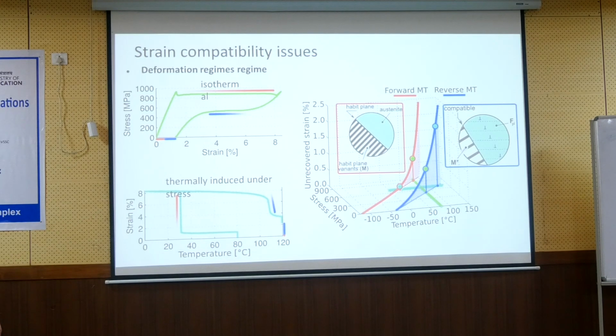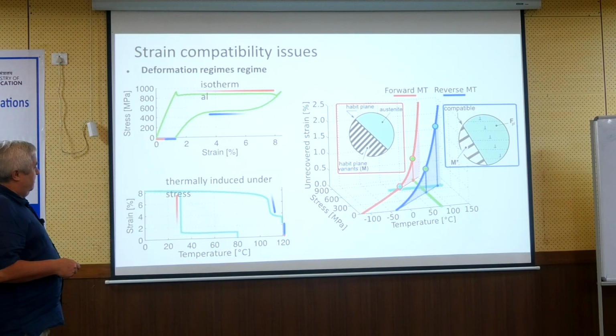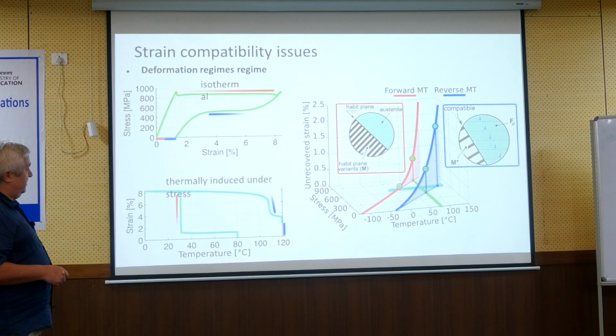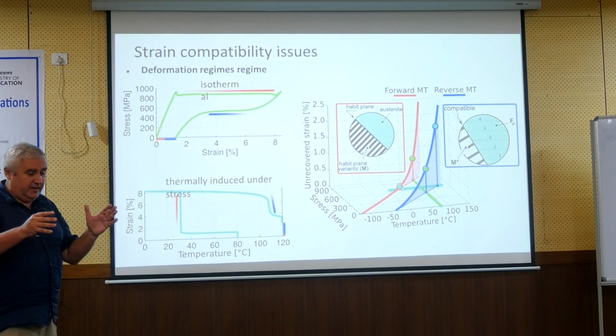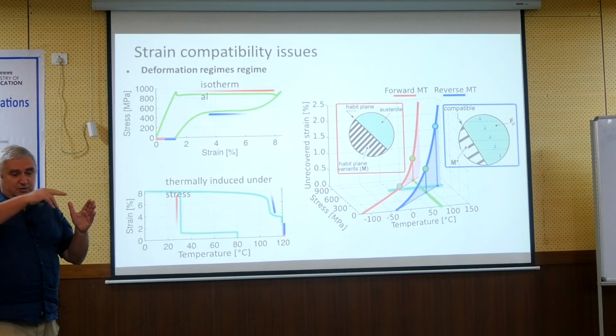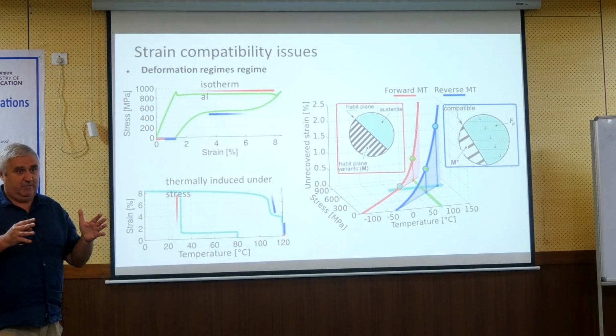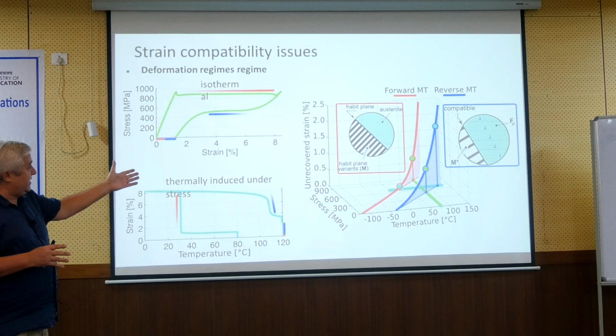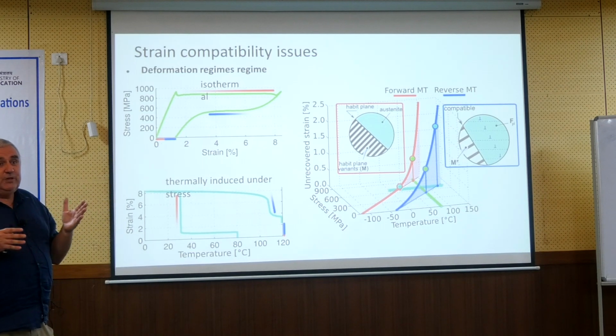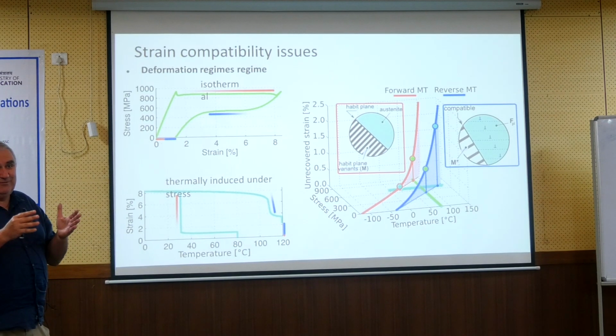So this right side curve, stress versus temperature, unrecovered strain. So this is for how many cycles? This is a specific experiment in which we measured it. What we did was take a NiTinol wire and apply 10 superelastic cycles, or 10 thermal cycles, or different kinds of cycles, but always 10 of them. You can plot the same image for just one cycle, but if you do it for just one cycle, because people know that the first cycle is different from the second one, they will not believe you. So that's why we measured 10 cycles.